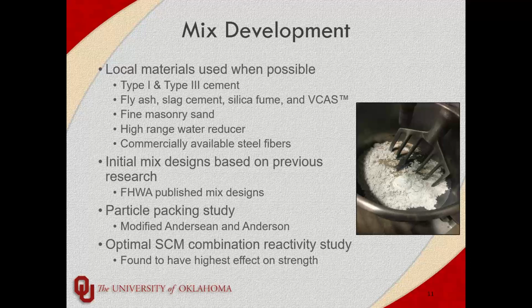Very similar to slag cement. Since it's produced, the gradation is more even, as well as the chemical composition. We use fine masonry sand, very similar to most other UHPC mixes, high range water reducer, and commercially available steel fibers. We started the process looking at some already published mix designs from the FHWA.